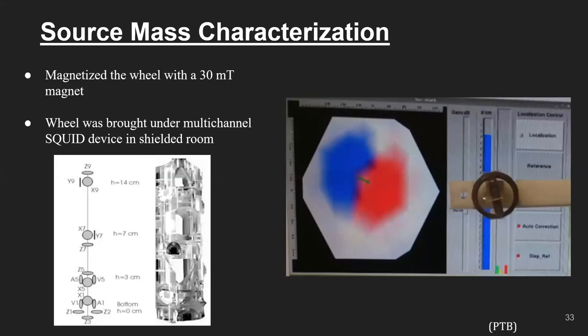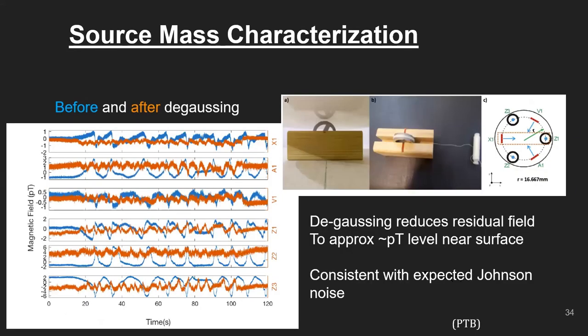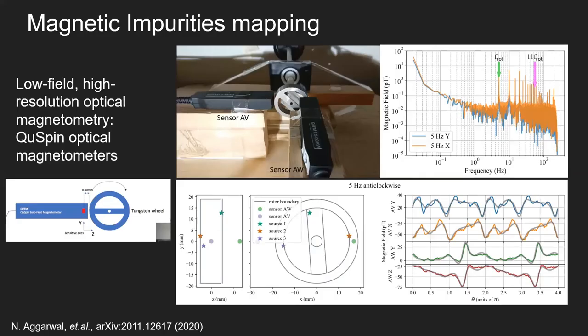That was tested in their SQUID magnetometer system, where they looked at the field before and after degaussing the rotor. The good news was that after degaussing the rotor, the field near the surface was at the level of picotesla, measured in their shielded room, which is consistent with what we'd expect from the Johnson noise. That should be tolerable if we're able to attain the superconducting shielding factor that we need from the thin film niobium.